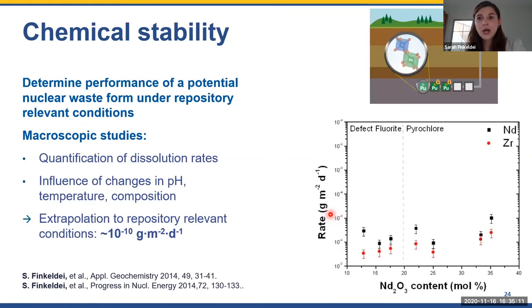And the last point that I would like to talk about on the waste forms is whenever we want to understand how a potential waste form would behave underground, in case all the technical barriers would fail, we can perform dissolution studies inside a laboratory, and we can derive dissolution rates that give us the possibility to extrapolate the dissolution rates of those materials under repository-relevant conditions when we study the pH dependence, temperature dependence, and composition dependence. What you can see here is that the dissolution rates are actually not going to drastically increase once we undergo this pyrochlore to defect fluorite order-disorder transition in response to self-irradiation of a potential waste form.